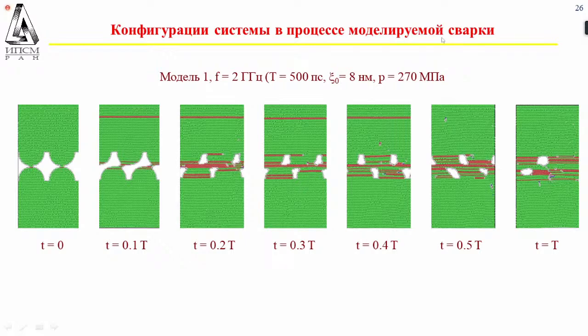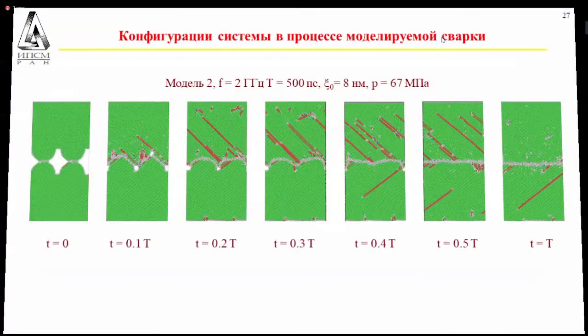Thus, there was a partial dislocation, which was developed from the surfaces of the pores, and there is intensive regeneration. And the plastic deformation, and we can see that there is no complete closure of pores with the amplitude at 8 nanometers and a pressure of 270 megapascals.